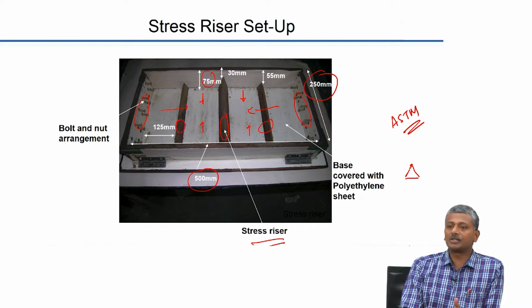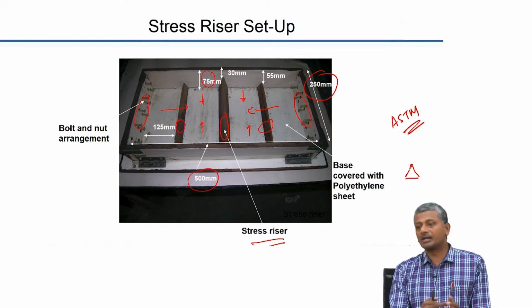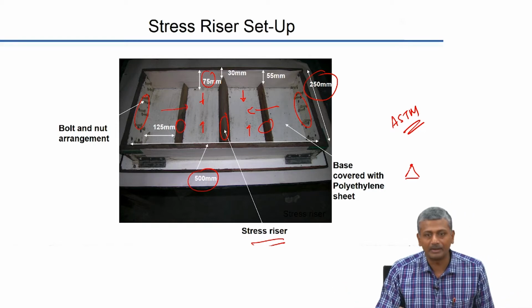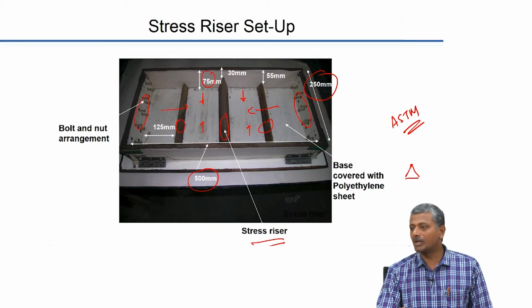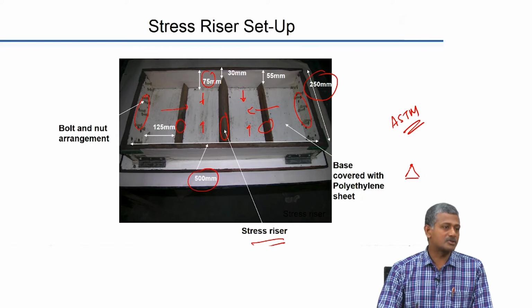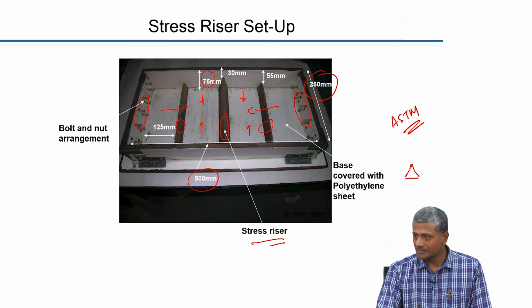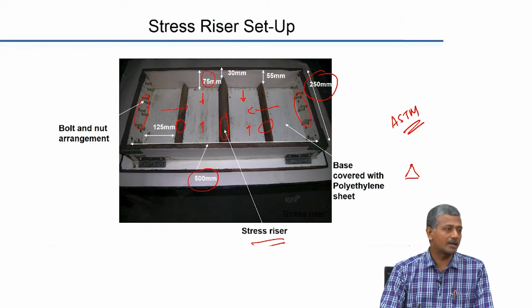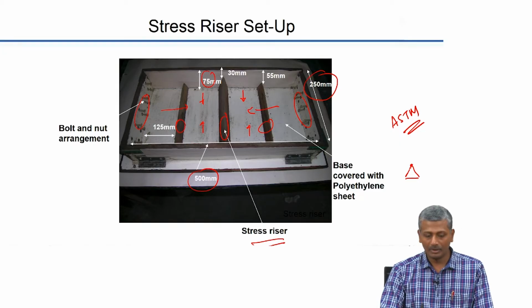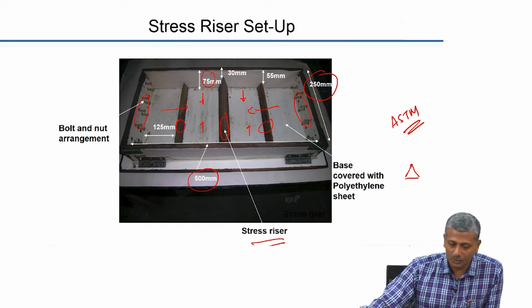So this makes the study of cracking much easier rather than looking at a very large slab where cracking can be quite random. In that case, doing a proper image analysis would require a lot of effort. In this case, because of the stress riser, the cracking appears very fast, and secondly, it is at a predetermined location, so you can actually study the characteristics of the crack much more easily. Okay. So this is basically the setup that was used.